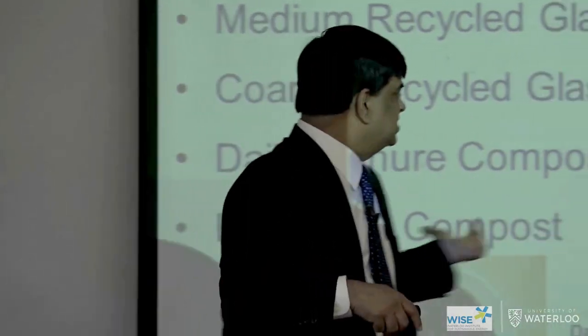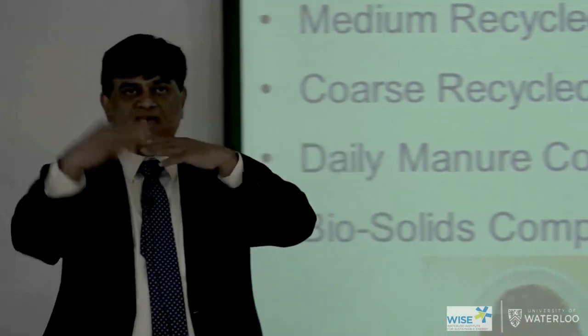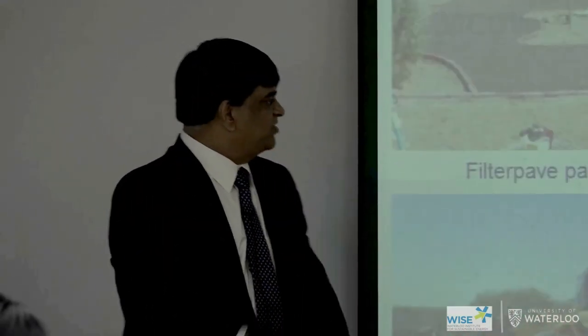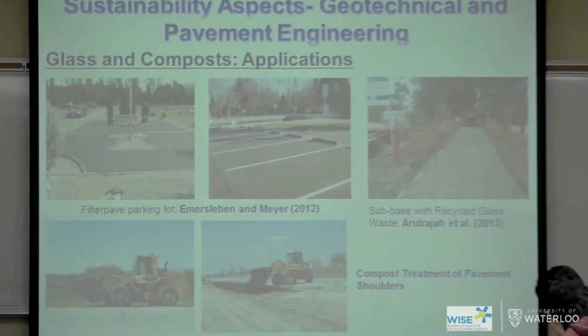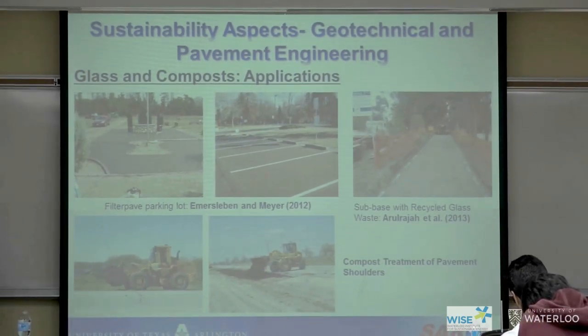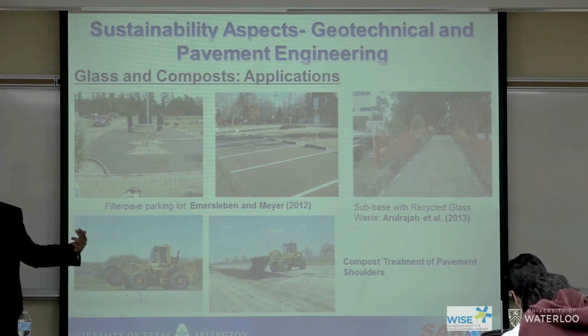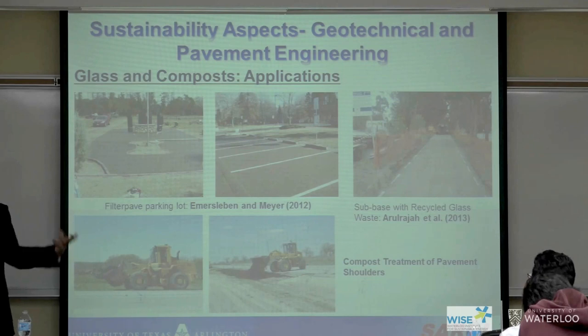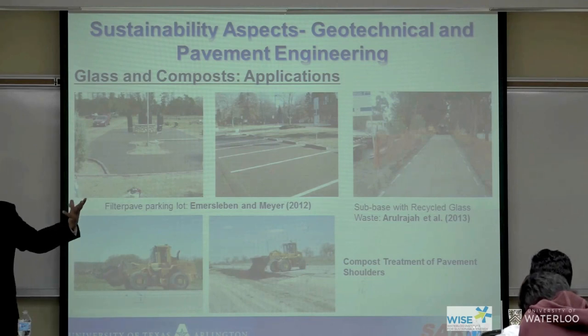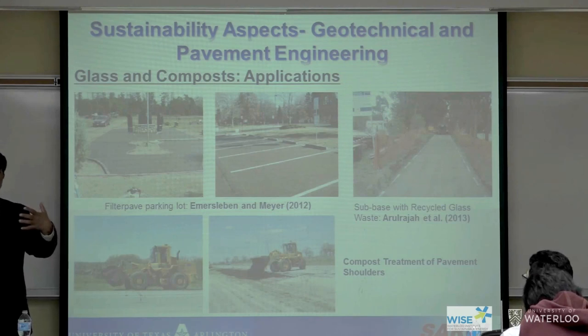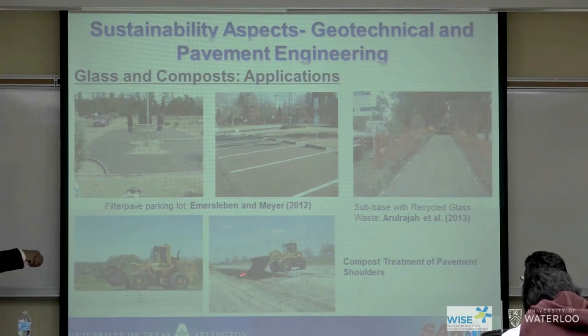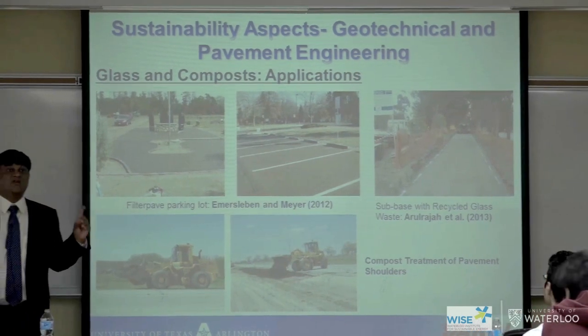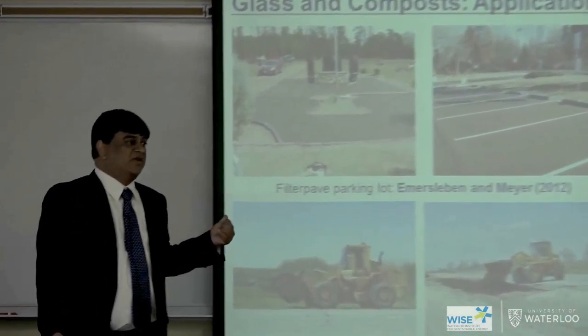So what we did is we used this compost material to create a soil mixture, and then we tried to use them here. In this project, where compost treatment was used on the shoulders, we mixed soil with the compost, and we put them on the shoulders. Most of the time our cracking comes from the shoulder. Shoulders crack because they're open and exposed to the sun, and then those cracks go into the travel lane, roads, and everything gets worse. So we demonstrated in a project. The dairy manure did not work very well. Biosolid compost worked very well.